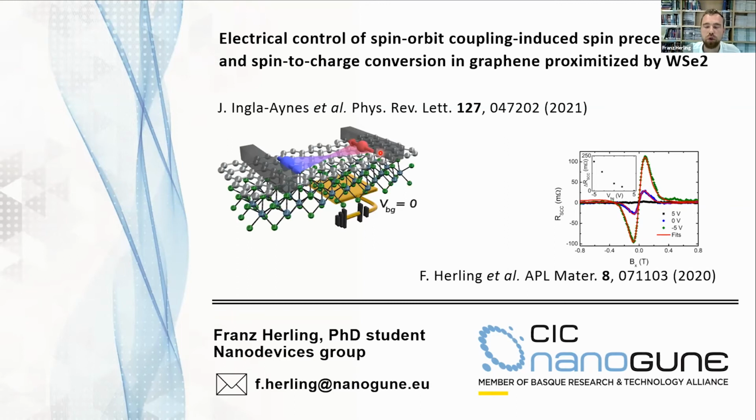Yeah. So theoretically, it's also possible to do out-of-plane precession, especially in the context of spin-to-charge conversion. This is an interesting topic, as you want to decide which spin-to-charge conversion mechanism you have. You want to measure spin precession out of plane or in plane to see if you're having an anti-symmetric Hanle curve, and then you can conclude if it's spin Hall effect or Edelstein effect.